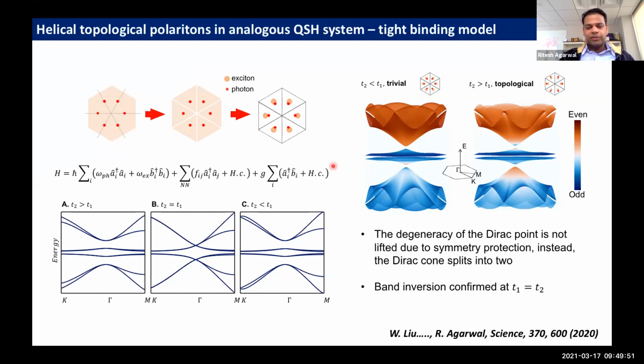So we write the tight binding Hamiltonian for this strongly coupled exciton-photonic system. We hybridize it, and then under the two regimes, the trivial regime or the non-trivial regime, we calculated the band structure. These are the three-dimensional band structures. Interestingly, by tuning a lot of parameters, we were able to find the regime where there is actually band inversion of these polaritons, of this coupled polaritonic system. You can see here it is blue, here it is red in the other regime, and vice versa in the conduction band. So this got us excited, that indeed we can get topological polaritons in the system.